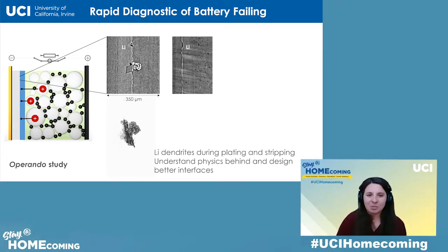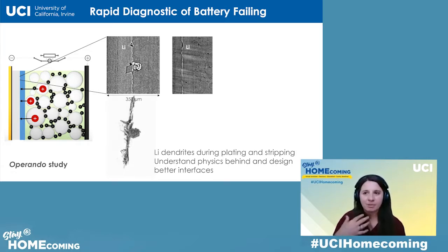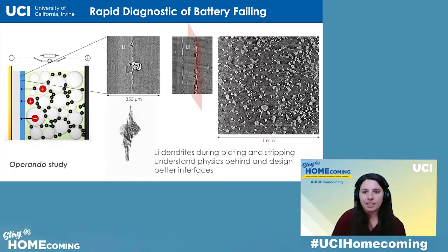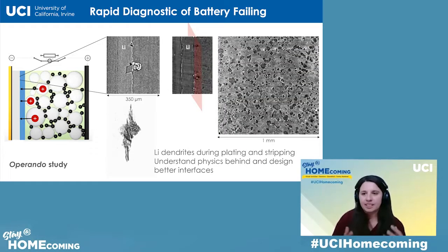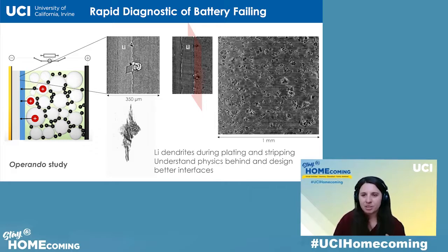So here is an example of dendrite growing on the anode, and also dendrite as a three-dimensional structure. While charging the battery, we managed to probe lithium plating in real life. Here is just a snapshot of the lithium dendrite, but we have the full 3D images of all the lithium battery. So looking at this interface, you can see that lithium plates very inhomogeneously.